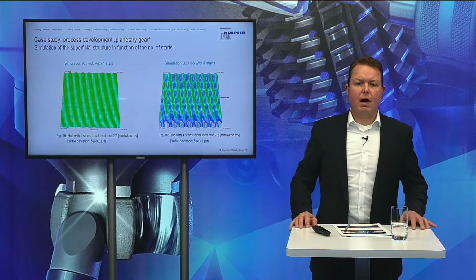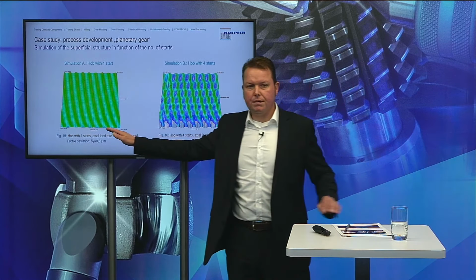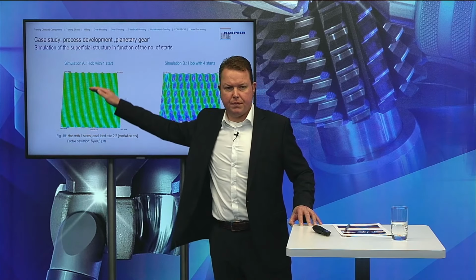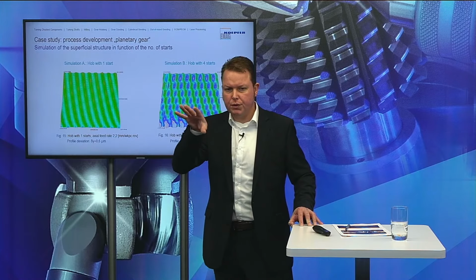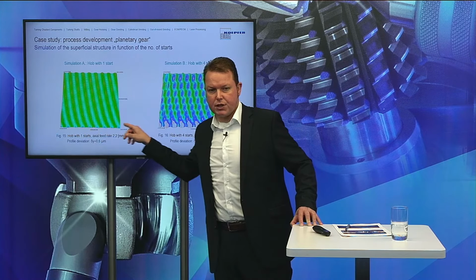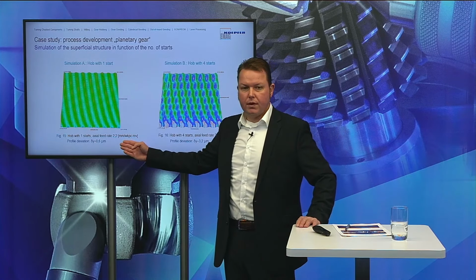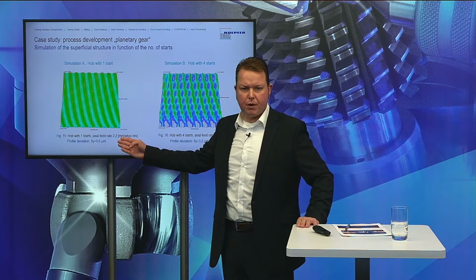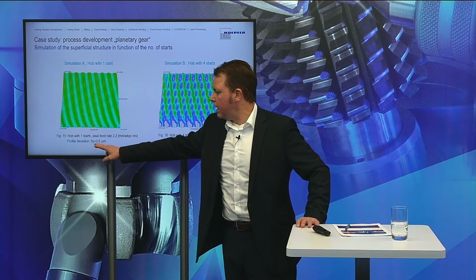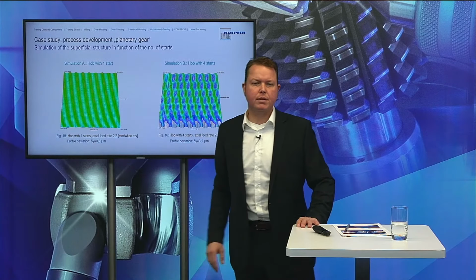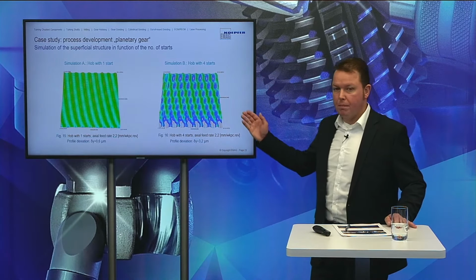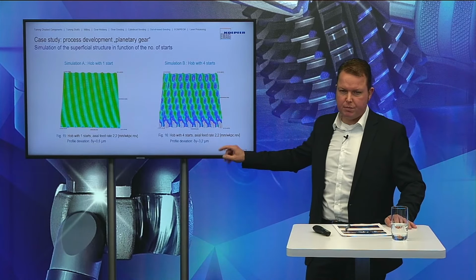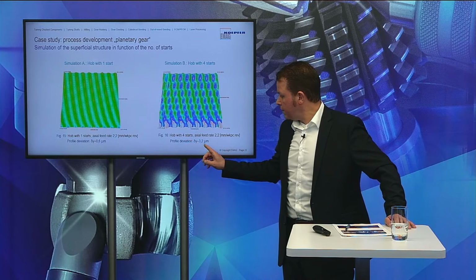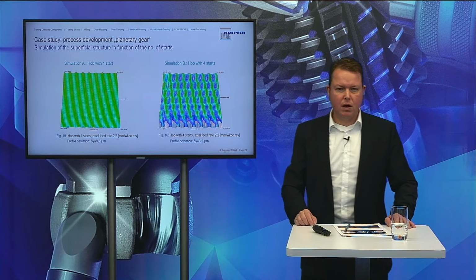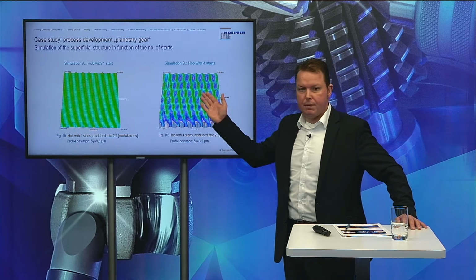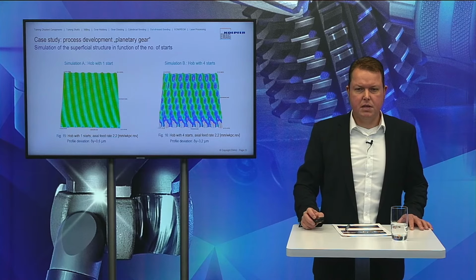Here is a simulation of our planetary gear. You can see the pictures in the root. This is the root of the tooth, and this is the tip of the tooth. So we are looking now onto the flank. This is the axial direction of the flank, and we see here a feed rate that has been simulated, 2.2 millimeters per workpiece revolution with a single start, and we have a delta Y profile deviation of 0.6 microns, so it's nearly negligible. And in comparison to this, we have exactly the same feed rate, but as a hob with 4 starts, and we have 3.2 microns of deviation. And you can see clearly that there is a huge difference as far as the topography of the teeth is concerned.